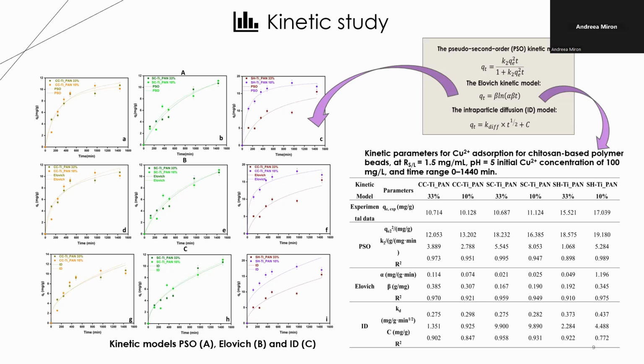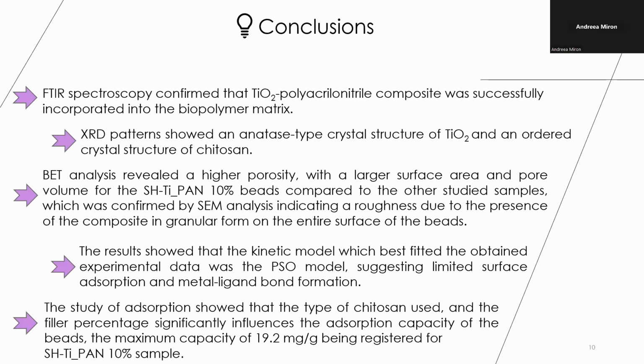To better understand the adsorption process, the pseudo second order kinetic, Elovich and intraparticle diffusion models were fit to the experimental data, and the parameters are summarized in the table. It can be seen that the best interpretation of the experimental data is given by the pseudo second order kinetic model. In conclusion, the spectroscopy confirmed that the titanium dioxide polyacrylonitrile composite was successfully incorporated in the biopolymer matrix.